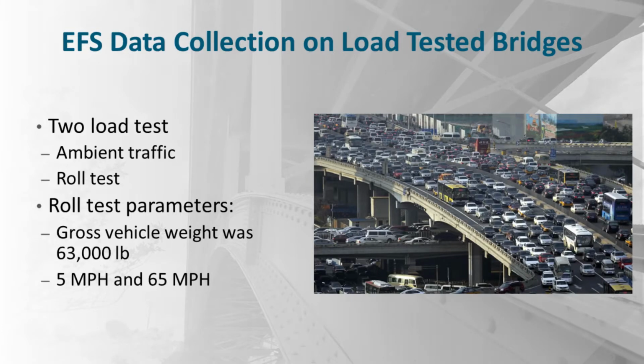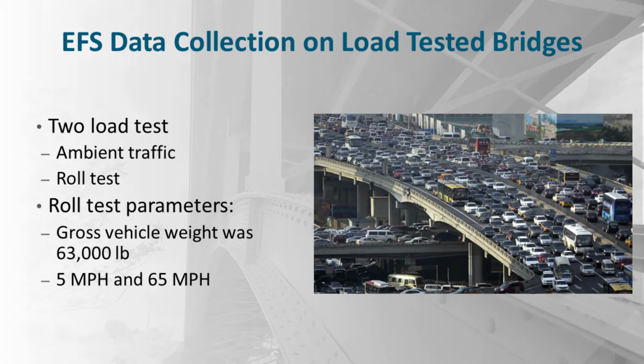Well, now that the EFS has been installed, what do we need to do in order to get some data? Well, we have 2 options pretty much: ambient traffic or do a roll test. If a roll test is an option, that will give you the results right away. If you use ambient traffic, we have to wait for a significant load to go over the bridge in order to get an accurate reading from the sensors. But in this case, we actually did both. We gathered data under ambient traffic and also roll test. For the roll test, we used 63,000 pounds in weight, and we used 2 different speeds. One was 5 miles per hour and the other 65 miles per hour.